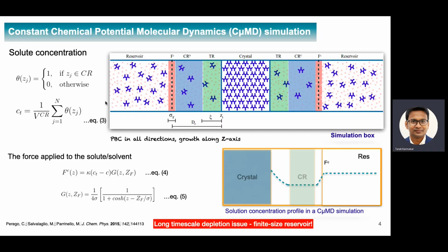Coming to the second part, while simulating crystallization from solution, we often consider a finite size system containing a few thousands of particles. Such a small system suffers from severe finite size effects. During crystallization, solutes are drawn from the solution to the growing crystal. This leads to solution depletion.